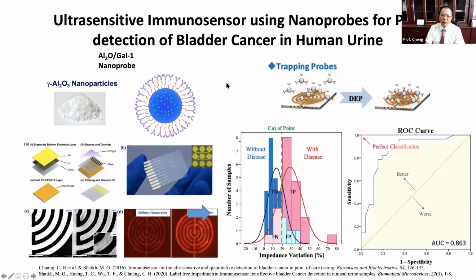In this research, we use a very low-cost nanoparticle, aluminum oxide. We modify the surface, and we can bind the antibody onto the surface. Using this nanoparticle, we use interdigital electrodes on the sensor. You can see this is our sensor. We use a very standard semiconductor process, and we can fabricate this sensor in my lab. We have the gold electrode, and you can see the modified image here. There are 3x3 gold electrodes, and they are all interdigital electrodes.